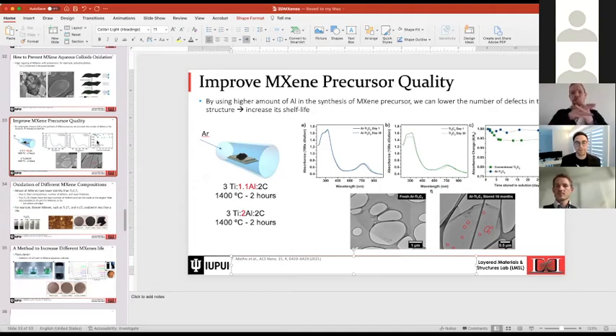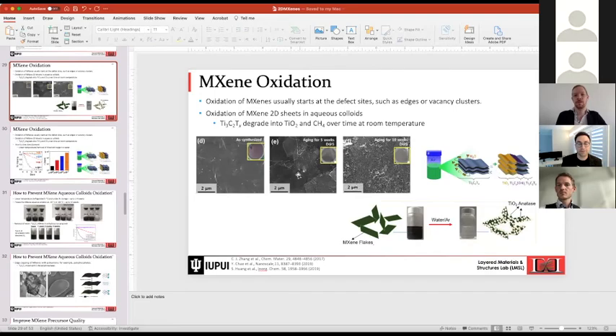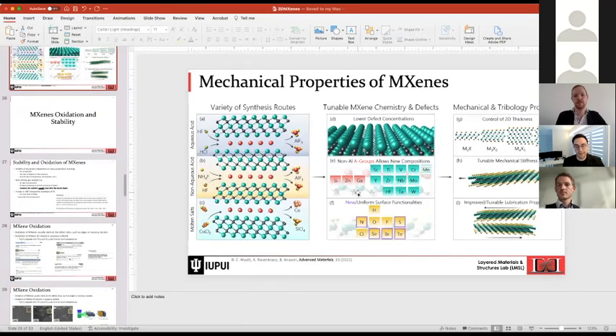For example, as I mentioned, the first nitride MXene, Ti4N3, was published in 2016 or 17, if I'm not mistaken. And that was published at Drexel, when I was at Drexel, when we used molten salt, because every time we tried the regular etching, which is hydrofluoric acid containing etching, everything would dissolve together and we would form a lot of oxides. So even forming the nitride would immediately turn into oxide. So stability is a major issue when designing all these carbides or nitrides. And now with the new methods of synthesis, such as molten salt, electrochemical etching, and others, I'm sure we can design more of the nitrides and investigate their properties. I believe that by having more variables in MXene, we can further tune the stability and mechanical properties for sure.